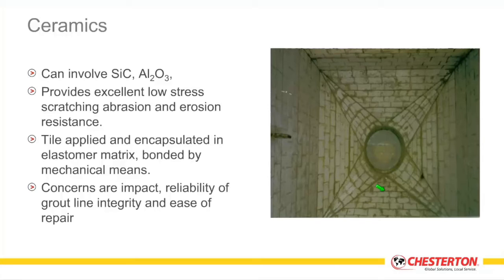Now, some of the issues that we find with ceramics is particularly related to the high angle of impact phases, where the brittle nature makes it more prone to cracking. And in many instances, if the tiles are laid and the grout lines wear out, you get grout erosion, and then you get undercutting and eddying, which can impact the adhesive layer, which can then result in tile disbondment. Once a tile is dislodged, if it is in the process flow, it now becomes a potential projectile, which can cause further damage downstream to process equipment or other lined areas. So again, when you want to consider any type of coating system, you also want to consider the mode of failure and the impact of that mode of failure to your process system.